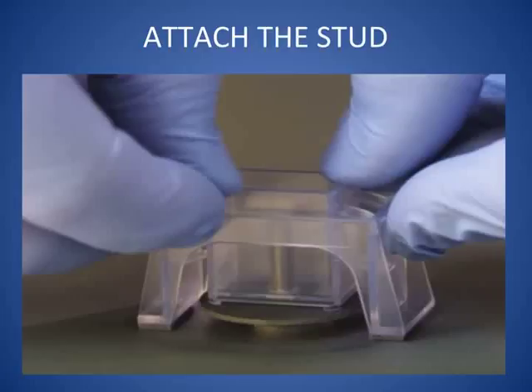Now, if you're hand applying it, that's going to make a big difference. If you're in a hot atmosphere and you're sticking it on by hand and you don't have this control, you could easily just squeeze most of the adhesive out, and that's just as bad as not having it. You have a too thin adhesive line. So there's a lot of variation in that, and that's one nice thing about this. It gives you a little quality control. All right. That's it on sticky stuff then.